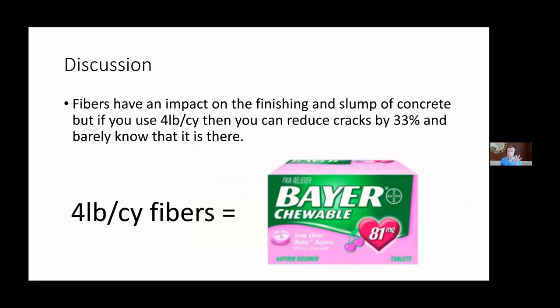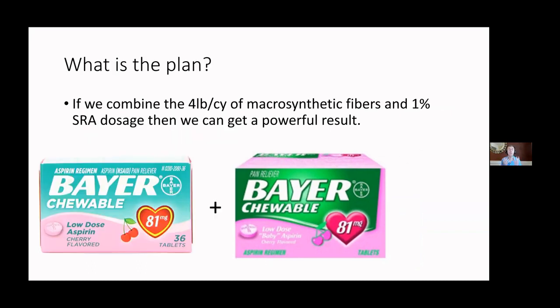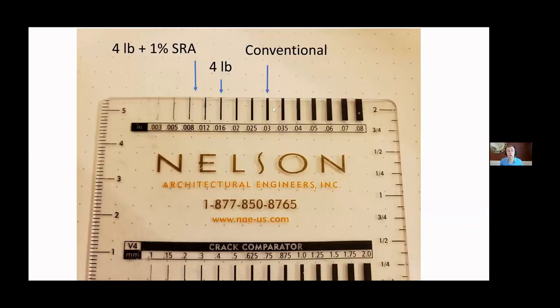And so 4 pounds per cubic yard, that's another baby aspirin, and that's what we want. So what's the plan? What if we combined this macrosynthetic, 4 pounds per cubic yard, baby aspirin number 2, and this 1% SRA, baby aspirin number 1, and we're going to get a powerful result. Pretty amazing. We're going to be able to go from conventional concrete cracking here to these things combined together to a 60% reduction in the crack size.